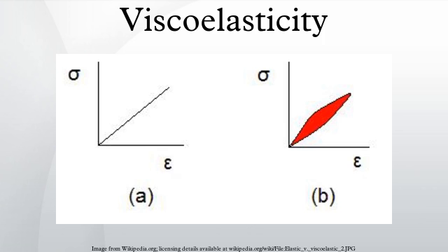Polymers remain a solid material even when these parts of their chains are rearranging in order to accommodate the stress, and as this occurs, it creates a back stress in the material. When the back stress is the same magnitude as the applied stress, the material no longer creeps. When the original stress is taken away, the accumulated back stresses will cause the polymer to return to its original form. The material creeps, which gives the prefix visco, and the material fully recovers, which gives the suffix elasticity.